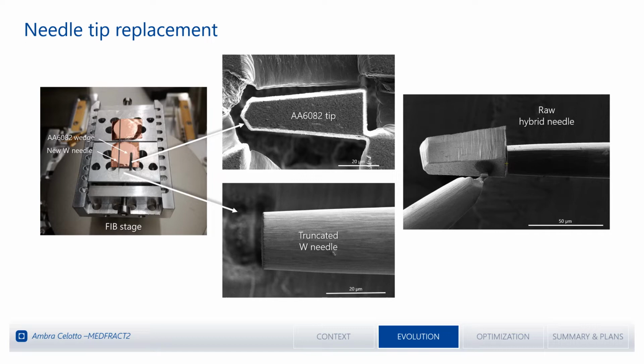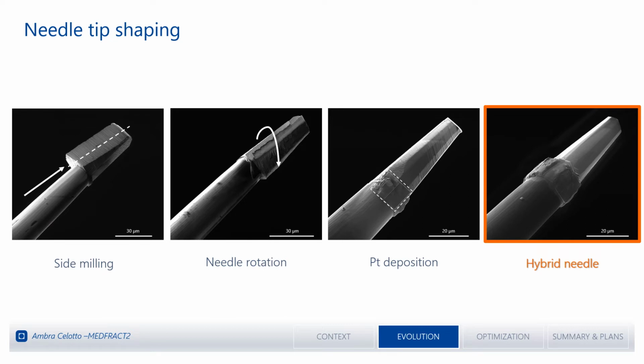Of course, to secure them together, we have to shave the exceeding part of the aluminium tip. And this shaping procedure takes place in this manner. So we take one side of the aluminium tip, we shave it, we rotate the needle, we add a small rectangle of platinum deposited on the interface, and then we keep on doing like this for all 360 degrees all around the needle in order to obtain, at the end, our hybrid needle. This will be fed in a base metal in order to be bonded with the base metal aluminium alloy.